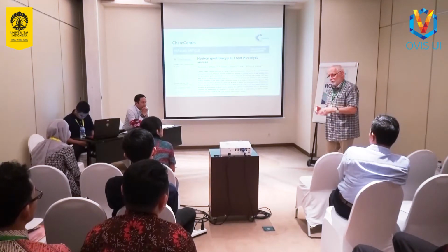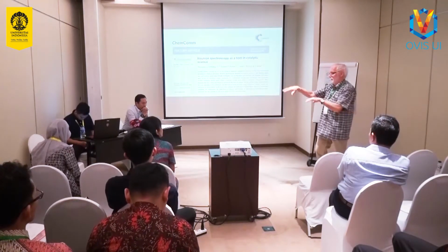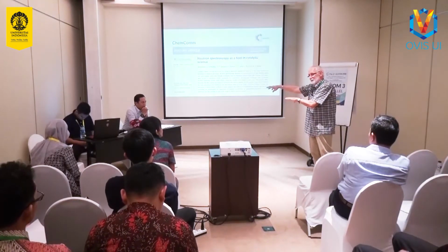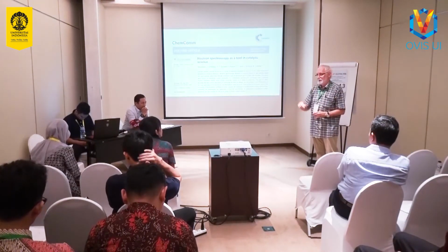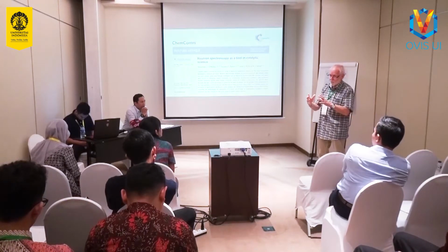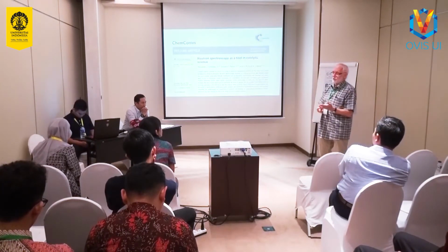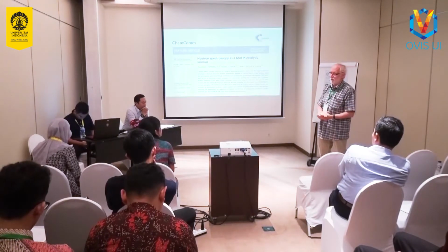So the chemistry is sort of similar: methanol, dimethyl ether, light olefins. In ZSM-5, the light olefins go on to make aromatics, but in smaller pore zeolites, you stop at light olefins. So your selectivity depends on the zeolite you use, pore size, but also on the temperature and the flow rate at which you're feeding the reactor. Those are all the variables that affect the selectivity.